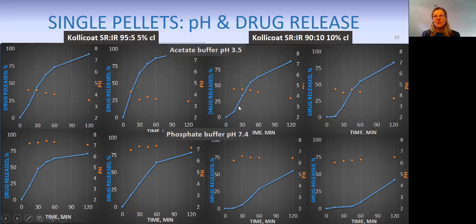You can see pellets exposed to acetate buffer do almost release all drug. The pH is going slowly towards 3.5. We're still a bit above because we've got some crystals remaining in the core. So same thing, we've got the buffer which is created. The second pellet, however, you can see is only releasing the drug after 15 minutes. So here we've got a lag time, meaning for a small moment we have no release, which has not been seen with the first pellet. So we've got really individual differences between the two pellets.